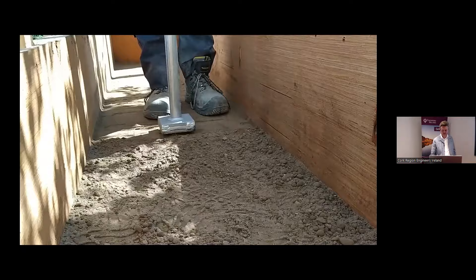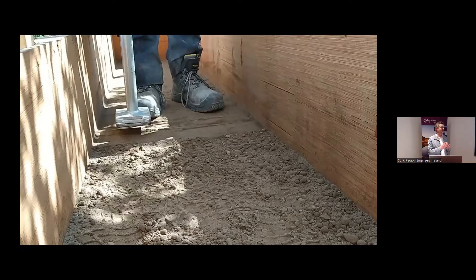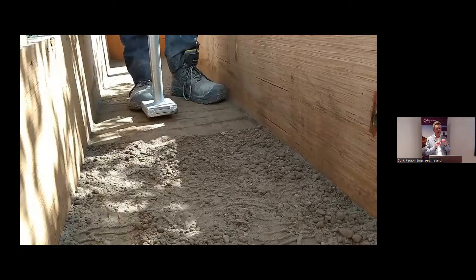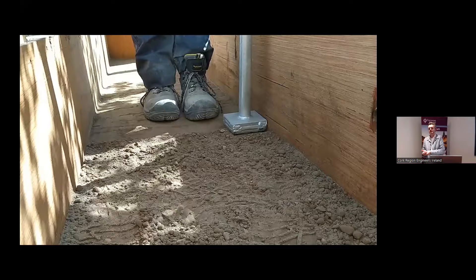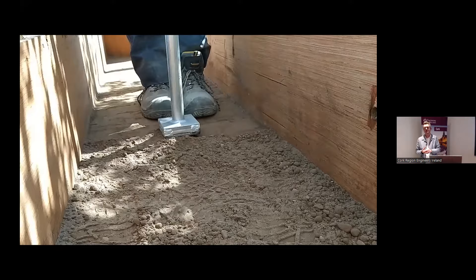The compaction process involves walking across and compacting down with your feet, then doing a 'soft ram' where you lift it up and slowly compact the earth into place. An interesting observation was that architecture students who were the best hand-drafters also had the best control with the rammer — they had the finest touch. For heavy ramming, you lift about 150mm above and drop it down repeatedly across the whole section. Intuitive signs of correct compaction include a hollow sound when compact, whereas incompletely compacted earth has a higher pitch tone. If you ball the earth in your hand, it should hold — too little clay and it breaks apart, too much clay and you can keep rolling it into a sausage shape.